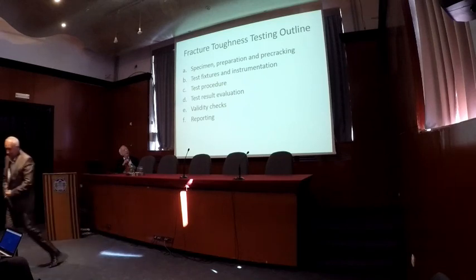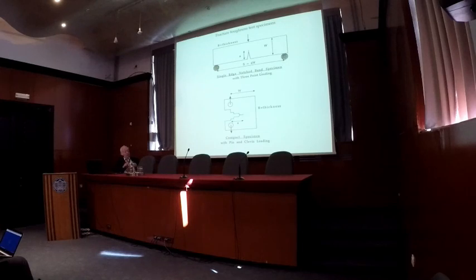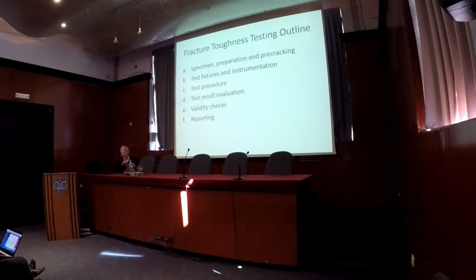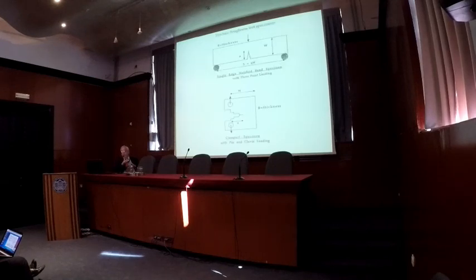You need to have a specimen. And here are the two main specimens used in most fracture mechanics standards. One is called compact specimen, or compact tension sometimes, and the other is bend. You need to have test fixtures to load your specimen. You need a procedure, you need a way to analyze the test, and then to do validity checks, and finally report. So here are the specimens,